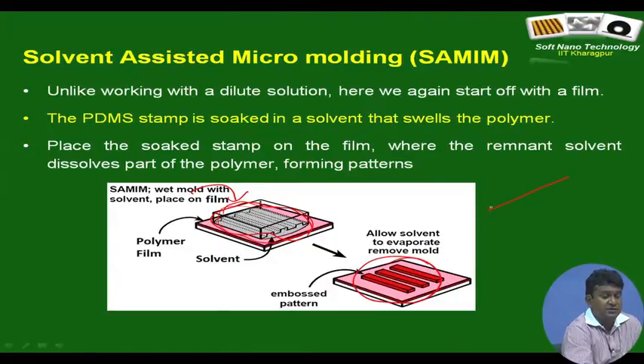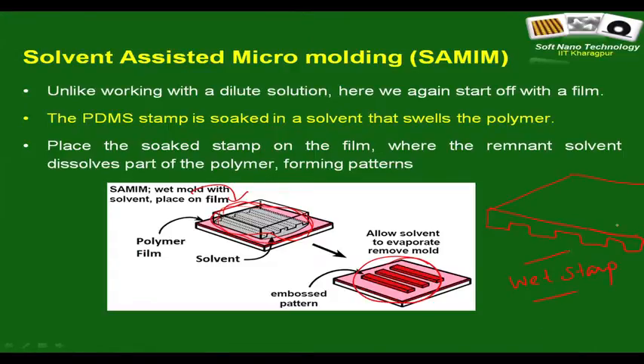When the stamp is coming, suppose this is the stamp you are bringing in, this is a wet stamp. The wet stamp itself is bringing the solvent. So, the problems associated with MIMIC, that due to capillarity, liquid does not reach the center of the stamp and long distances from the edges, are completely eliminated. But honestly speaking, as a concept, this is very good, because you still do not need any thermal cycling, you do not need to apply high pressure, but then pattern uniformity control is a critical issue.